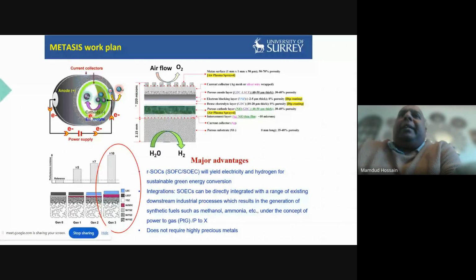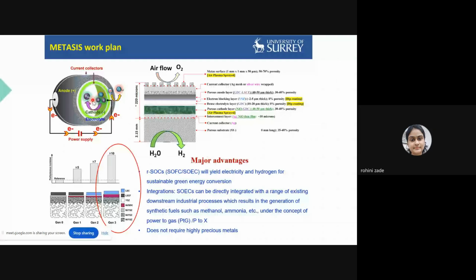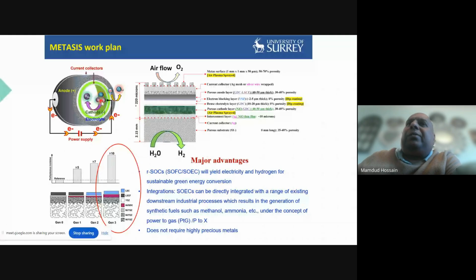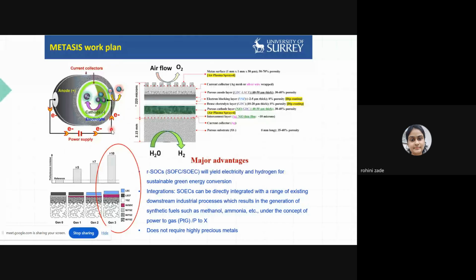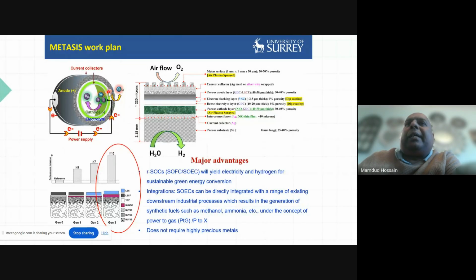What will happen is your water, in steam form, will break down. H2O is split into hydrogen and oxygen. The hydrogen combines together to create hydrogen gas, and we are left with an oxygen ion, because oxygen takes in two electrons, becoming an oxygen ion. This oxygen ion can then flow through the electrolyte. The electrolyte only allows oxygen ions to flow through. It blocks hydrogen, it blocks steam, and it blocks electrons. So the oxygen ion flows through the electrolyte to the other side.